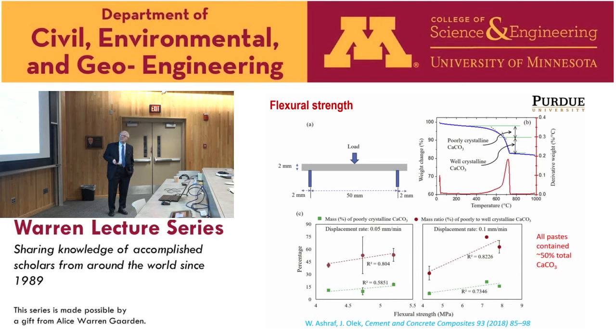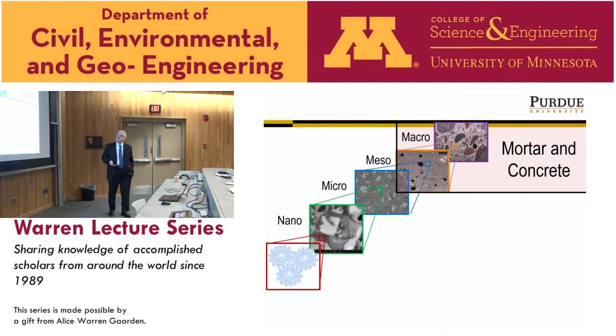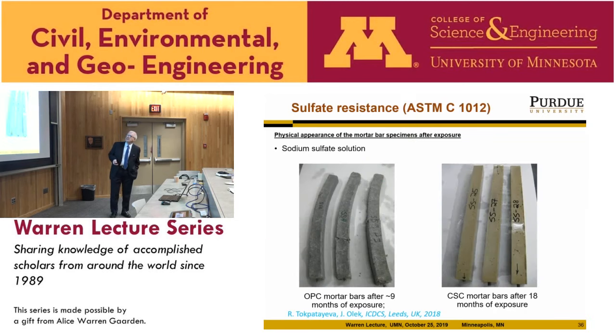We've done some evaluation of the mechanical properties. You know, all the pastes contained about 50% of calcium carbonate, but that's the global number. What is the percentage of vaterite? What is the percentage of aragonite? What is the percentage of calcite? That's what we determine, and you can see a very nice trend here. The higher amount of amorphous material, the higher the value of flexural strength, for example, right? So the phase composition has the influence on mechanical properties.